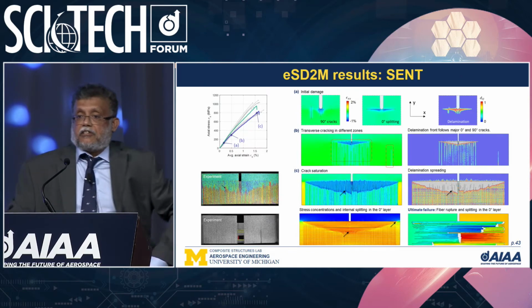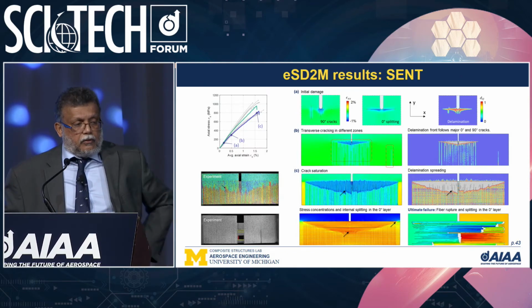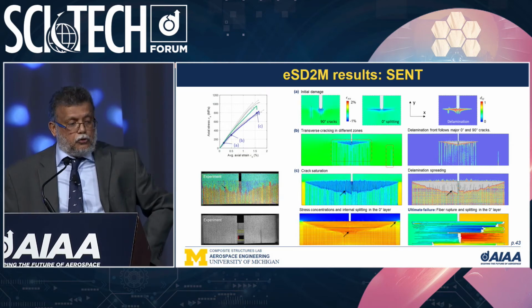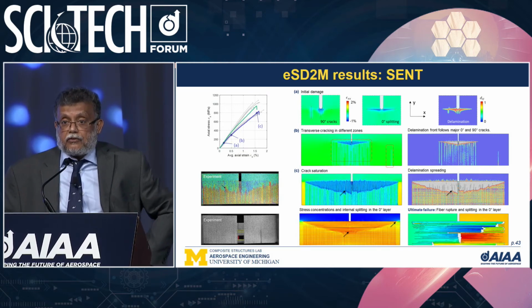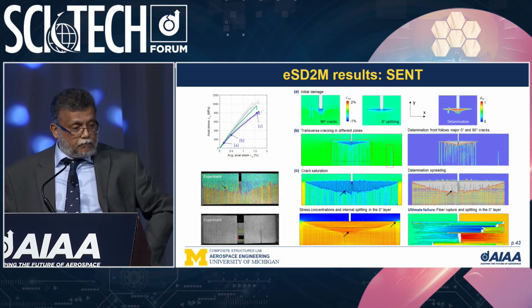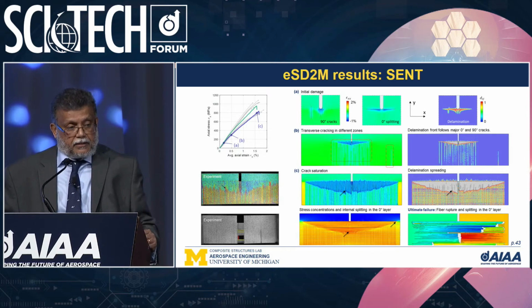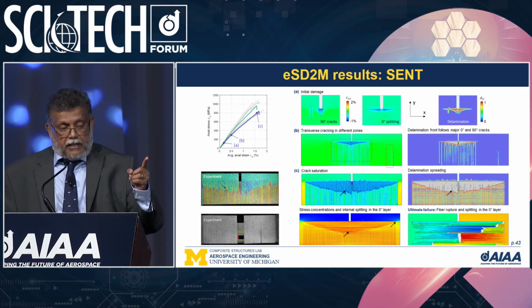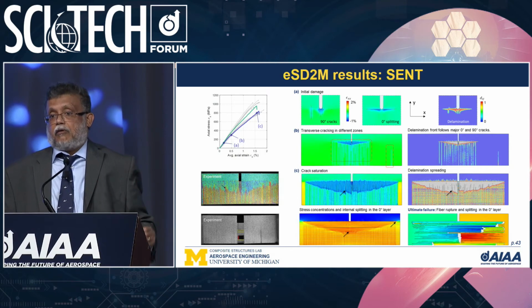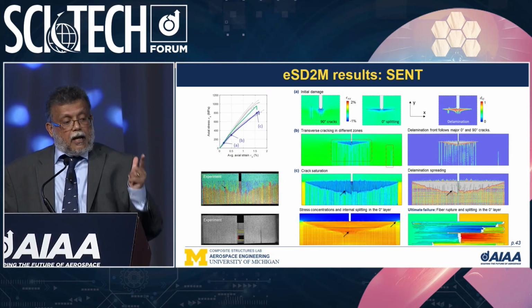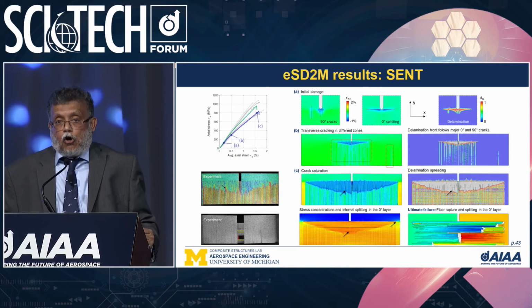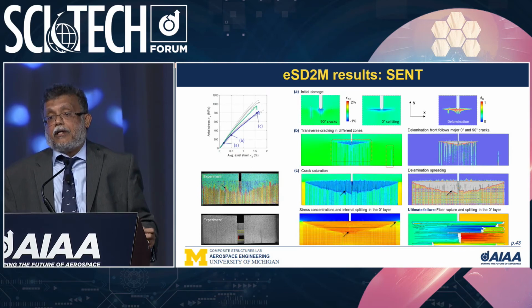So these are the pictures that you get in the experiments, and on the right hand side I show you the actual predictions by the ESD2M model. You get the delamination predicted correctly, the matrix cracking and the evolution of the cracking predicted correctly, and finally the rupture also predicted correctly and accurately.